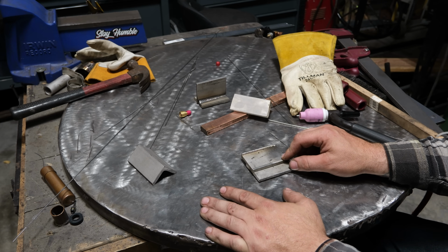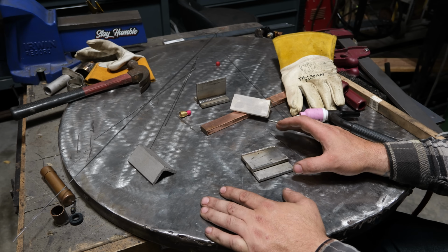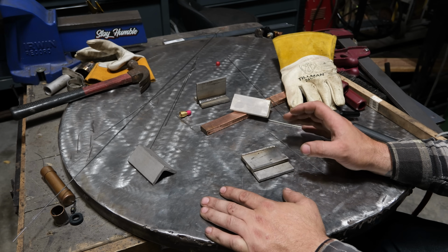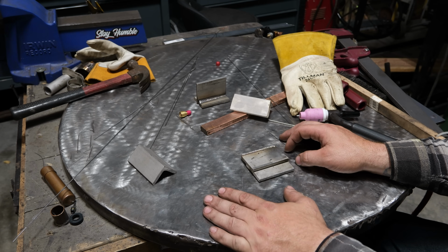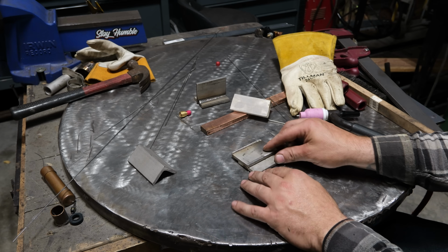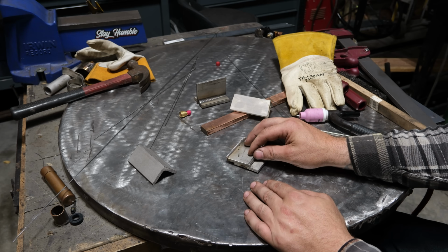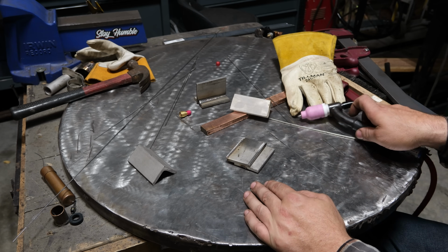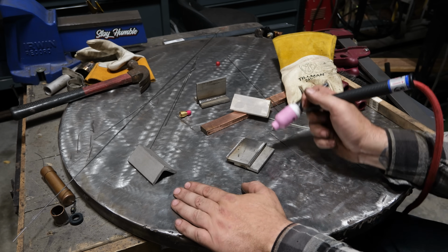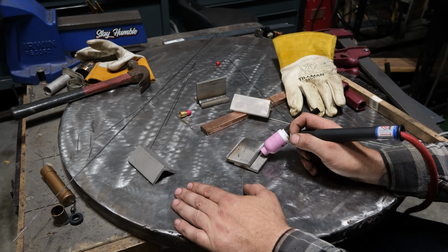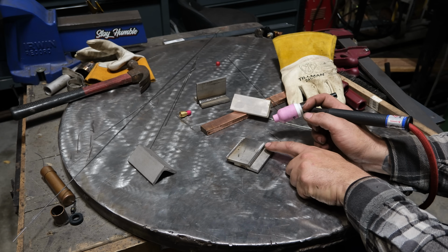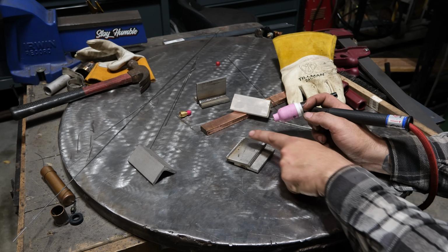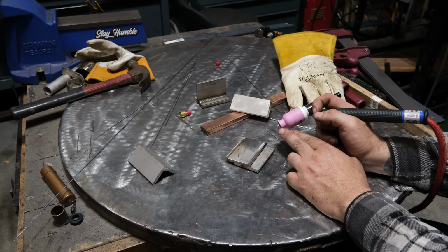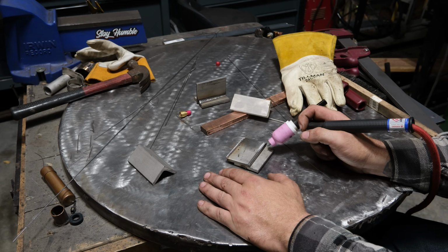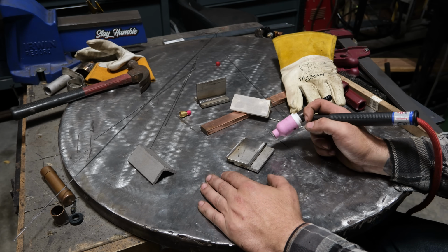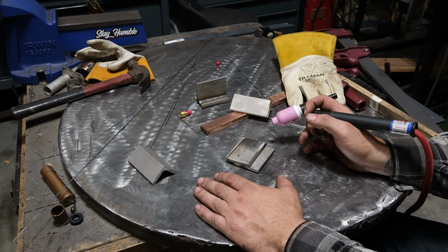If you find yourself welding lap welds a lot, or you have one that you need to do and you need to have no sugaring, aka a very clean, very good looking weld, it can be pretty tricky. It doesn't really matter if it's thin or thick, though if anything, thinner material is harder to get good results on. You're welding it like this and you end up having an issue where the argon gets split by the edge and flows out over, maybe it sucks oxygen from behind the cup. Long story short, you can't get a real clean, at least decent looking weld, and it's turning gray.